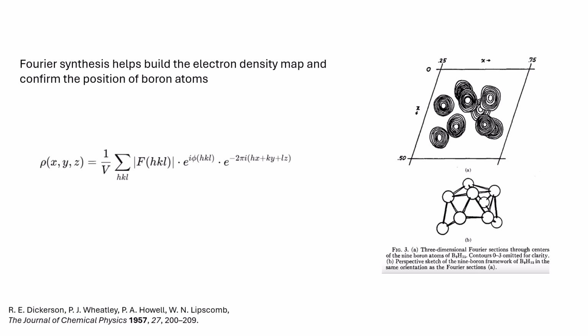The exponential term introduces the phase shifts that vary with position, and by summing all these waves' contributions, the electron density distribution is constructed in real space. This allows chemists to visualize atomic positions and bonding in a crystal. Shown in the plot right here is the structure and the electronic density map built up by Lipscomb in his paper back in 1957.